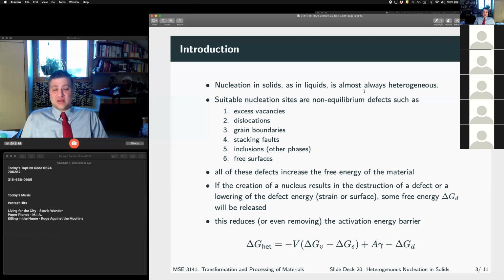They are not the thermodynamically stable phase. Right? So in liquids, we nucleated at mold walls or other solids or junk that's floating around in our liquid. In solids, where are we going to nucleate? Well, we can nucleate on excess vacancies, dislocations, grain boundaries, stacking faults, or other special interfaces. Inclusions, meaning other phases that are there, right? So very often, like we'll see in aluminum copper, the thermodynamically stable phases nucleate heterogeneously from the intermediate phases and free surfaces.